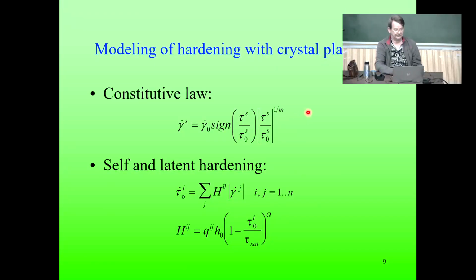And then this part in the crystal plasticity simulation, you have this constitutive law with the strain rate sensitivity, which is relating the local shear stress in the slip system to the slip rate. We have self and latent hardening, a sophisticated one, with this hardening matrix, so that the slip in all the slip systems produces increments in the strength of the slip systems. And then this hardening matrix is controlled by parameters H0, tau sat, and A.